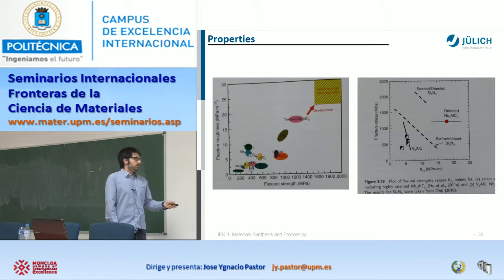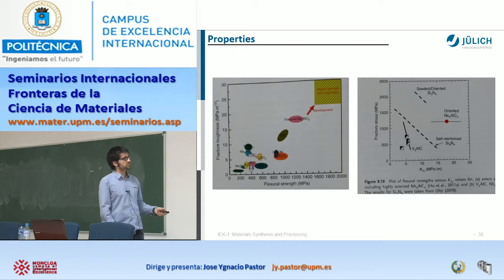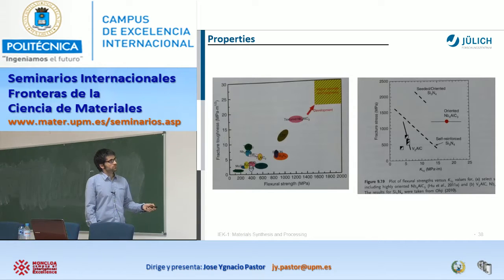And well, here now another plot to have an idea where we can locate the materials. This is fracture stress as a function of fracture toughness. Again, as always, if in ceramics we talk about fracture toughness, normally silicon nitride is one of the best materials, and then there are these here, or also here, if you put seeds of this silicon nitride to have really elongated beta phases. But okay, we are talking that we can even improve these values.